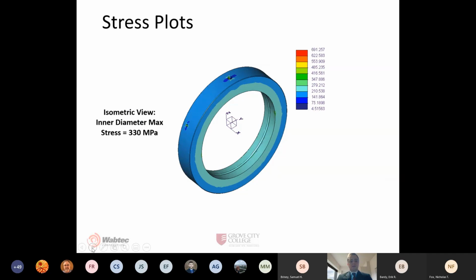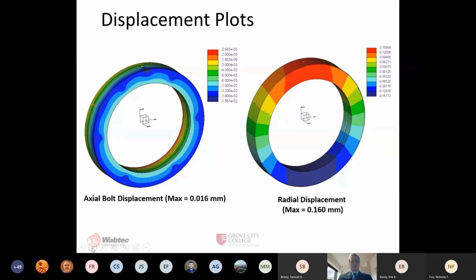And this plot shows the stress on the inner diameter, which is the lowest stress in terms of critical areas, at around 330 megapascals. And here are the displacement plots for the collar. The axial bolt displacement plot is shown to the left, and visually can be seen by the 6 circular surface regions on the plot. And the radial displacement plot is shown to the right, showing displacement in the vertical direction. Now Kyle will take over and talk about the backing plate.